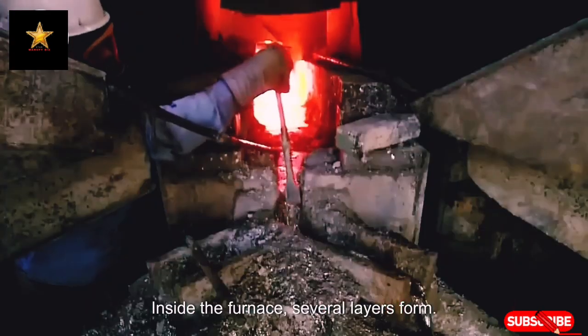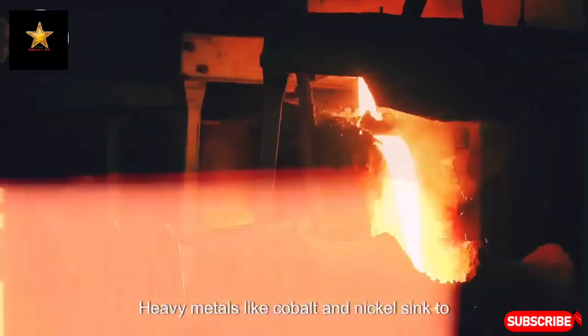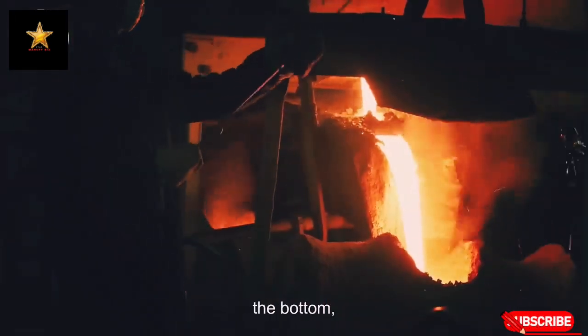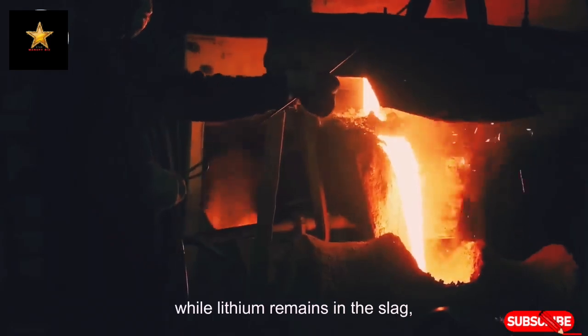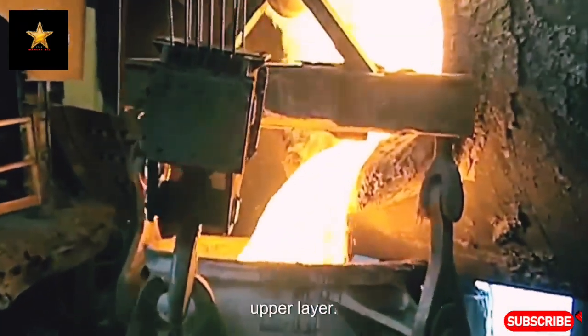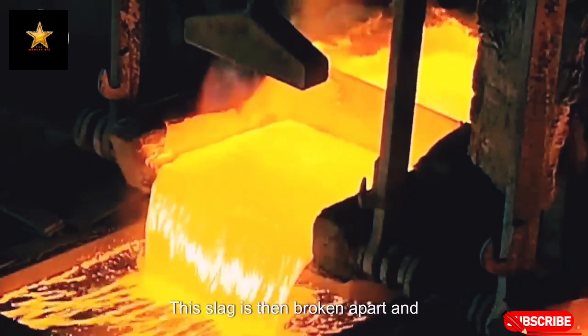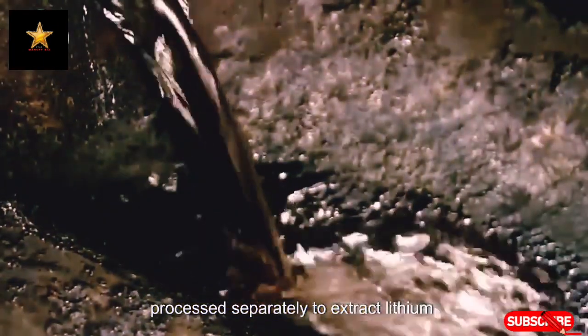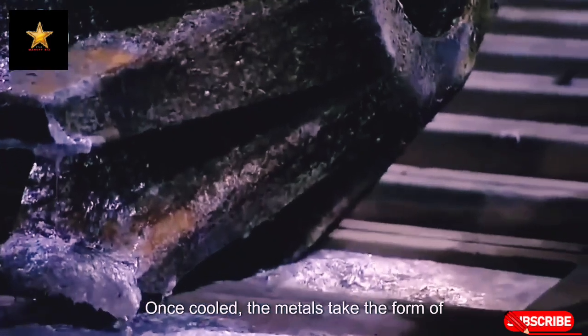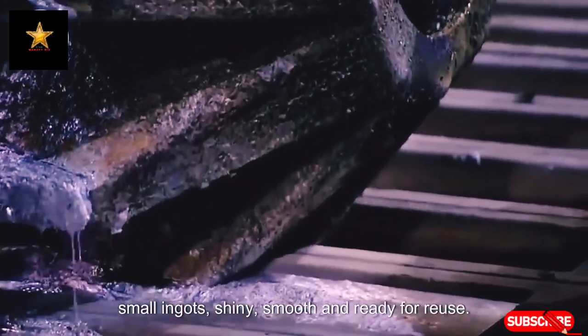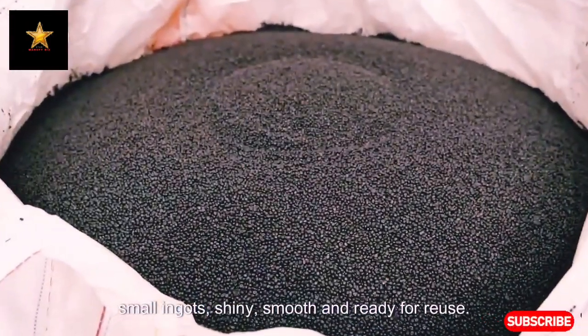Inside the furnace, several layers form. Heavy metals like cobalt and nickel sink to the bottom, while lithium remains in the slag, the lighter, upper layer. This slag is then broken apart and processed separately to extract lithium. Once cooled, the metals take the form of small ingots, shiny, smooth, and ready for reuse.